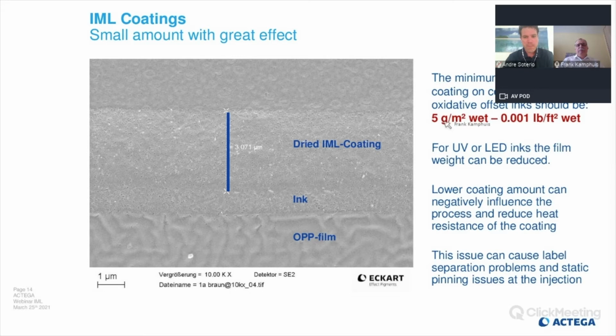For applying oxidative inks, you need a minimum of 5 grams per square meter wet of a coating. That's 0.001 pounds per square foot. For UV inks and LED inks, you can reduce a little bit. But if the coating amount is too low, you get problems in further processing.